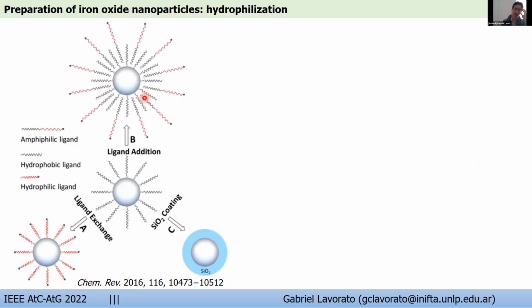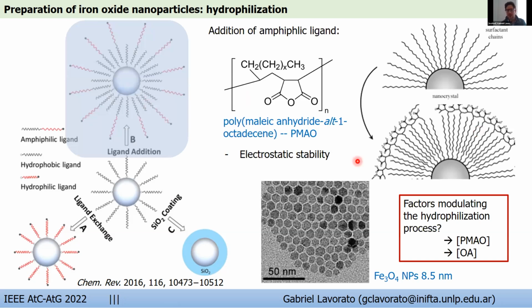However, most applications require water dispersible nanoparticles. So to obtain them, the oleate capping can be replaced with hydrophilic molecules or with a silica coating. And a third option consists in adding an amphiphilic ligand to this surface that interdigitates with the oleate capping at the nanoparticle surface. So a convenient way to do this is by using, for example, PMAO, which is a polymer with long hydrocarbon chains that in alkaline media leaves exposed carboxylate entities, which provide electrostatic stability to the colloid.